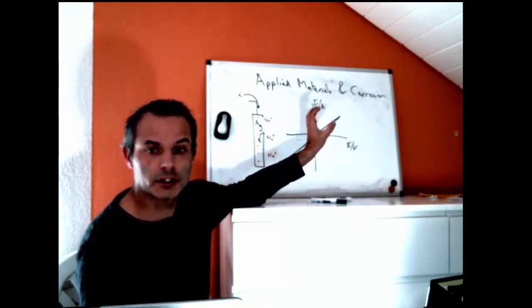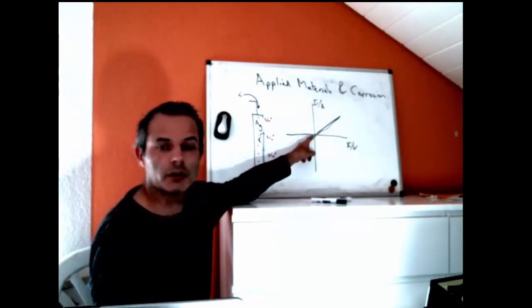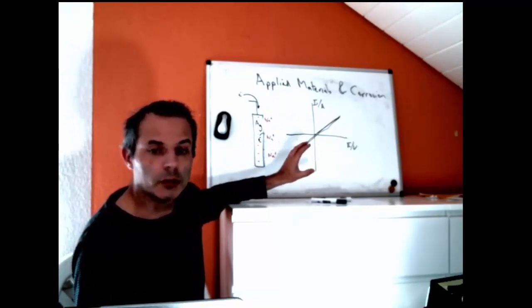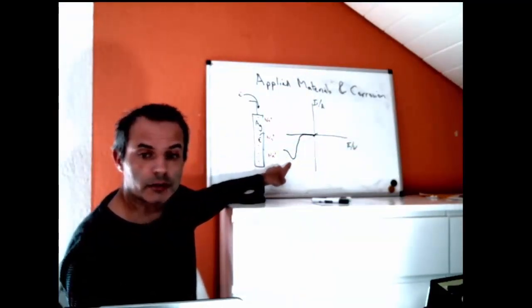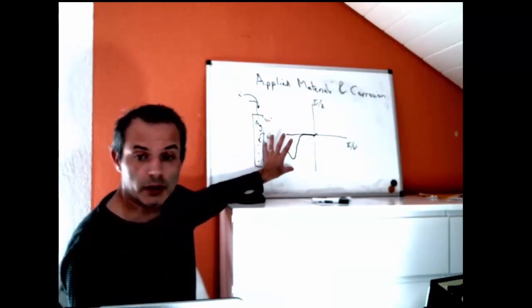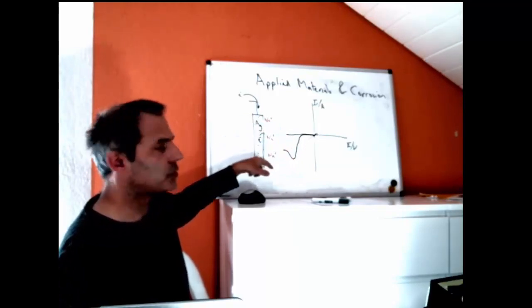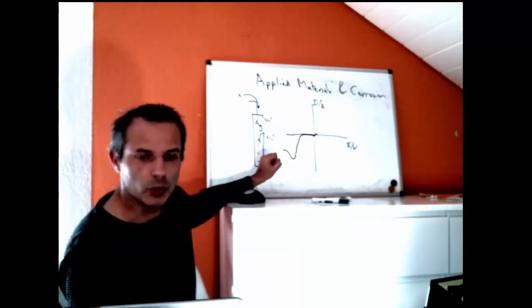So there is a disadvantage to sweeping the voltage faster. The faster we sweep the voltage, the more current we get from this effect, which we probably don't want to measure. Remember, this was the shape of the curve that we would get normally with our reagent, so we need to add that to the shape of the charging the capacitor curve depending on what we get.